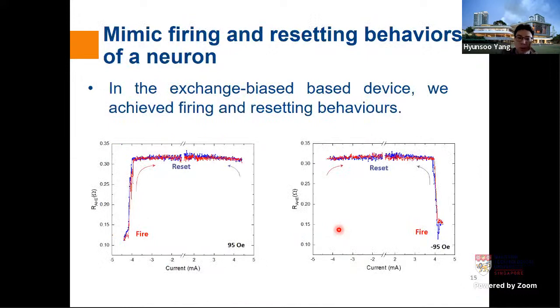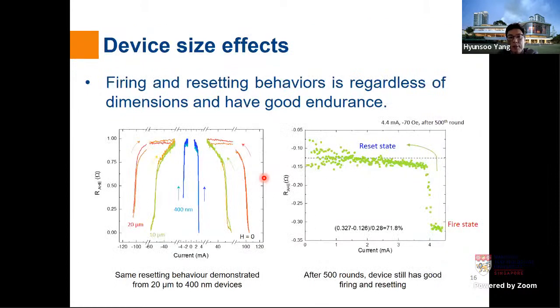So experimentally, we show having such exchange bias, the SOT, you can increase your current in the heavy metal and you can fire. That means you switch your magnetization into a certain direction. Then once you bring back your current to almost zero, you can see the signal will follow the first trajectory, the switching trajectory, and then go back to the initial state. And that is also tunable depending on the in-plane assisted magnetic field, because right now we are dealing with very simple heavy metal. So we need the external small magnetic field for assisted deterministic switching.